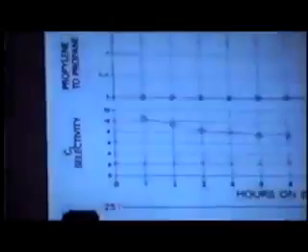The propylene to propane ratio is about 1.2, significantly higher than what we see with the highly dispersed catalyst. And this supports our hypothesis that in the absence of hydrogen generation through the water gas shift reaction, you can obtain an olefin to paraffin ratio of about 1 with this catalyst. Now the methane selectivity is significantly lower with the intermediate size ruthenium particle catalyst. Lower methane selectivity implies higher chain growth probability in this reaction.